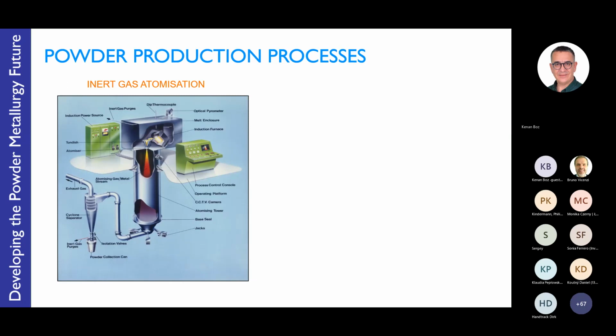So the molten material is sourced from scrap materials or alloyed in situ to create a diverse range of different materials, typically top poured, sometimes bottom poured, into a tundish, usually a conical shaped tundish, and the molten material then is drawn into the atomizer and impacted by high pressure gas, which can be in various different arrangements, from close coupled atomization of fine powder to two-stage atomizers for mid and coarse size fractions. So you can atomize different size distributions based on the configuration of the atomizer.